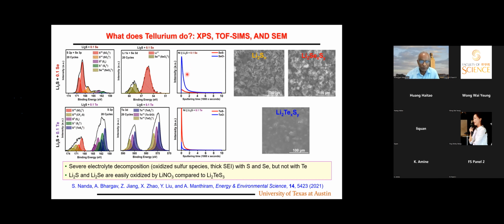Exactly the opposite. Here blue is more, here red is more. So you can clearly see. If you look at the lithium morphology after cycling, you have rough morphology. With tellurium addition, you have better morphology.